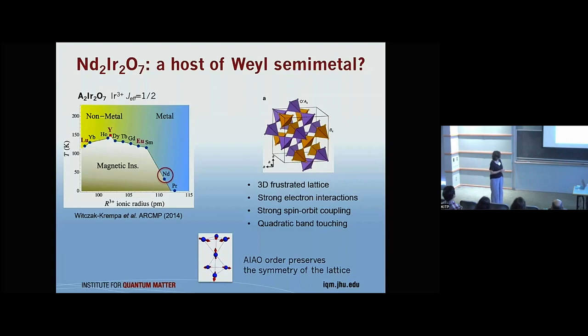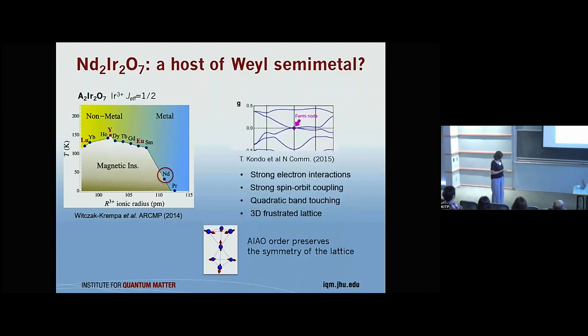Neodymium iridate is the most interesting material in that it does have a magnetic transition at 33K and another one later. So neodymium iridate was the most interesting in this phase diagram from the point of view of topological states. So why did we study topological states? The suggestion was that in pyrochlore iridates there is a topologically protected metallic or semi-metallic state.